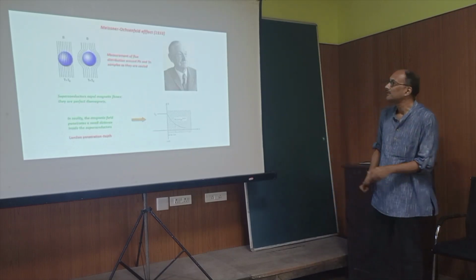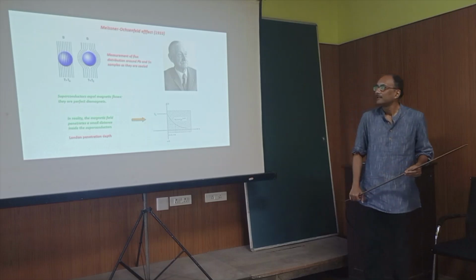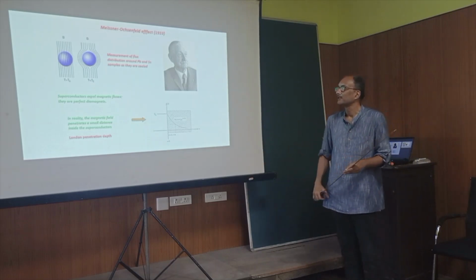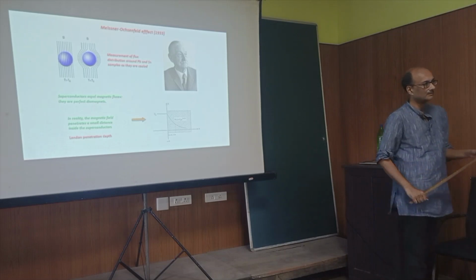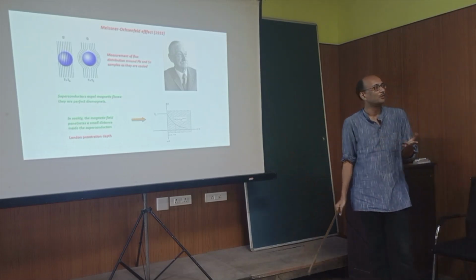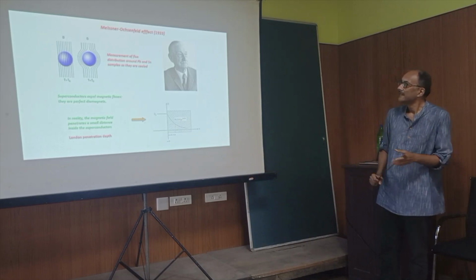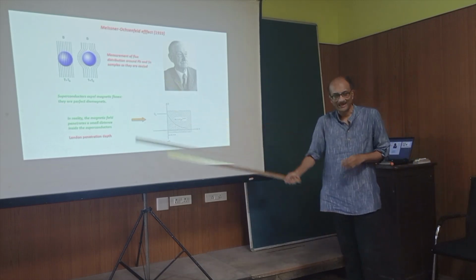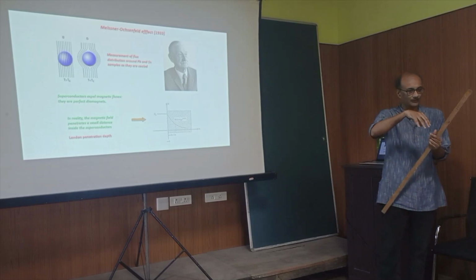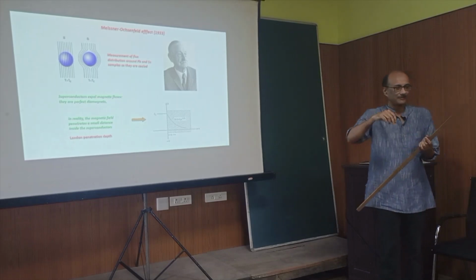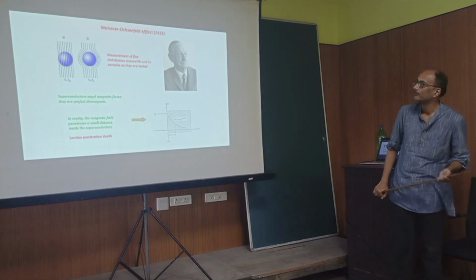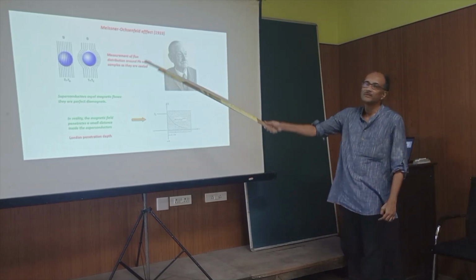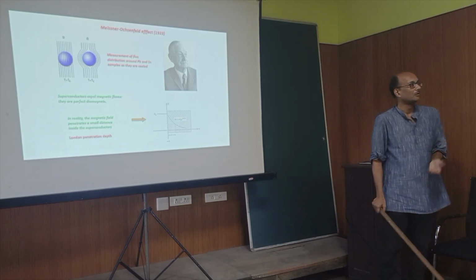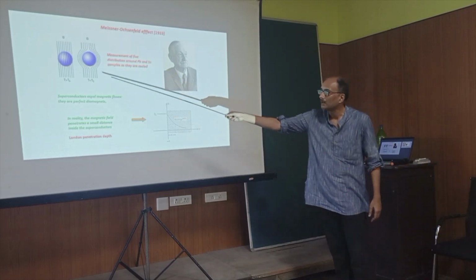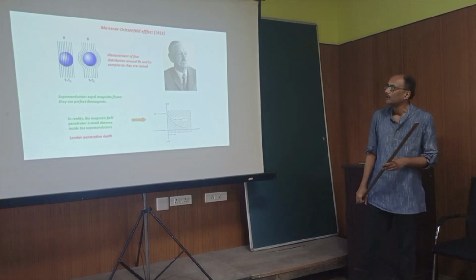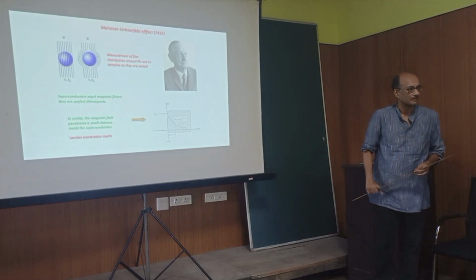when this gentleman, Meissner, and his student Ostenfeld essentially found out something really interesting. So this was about 21 years from 1912. Okay? So what they found is that they were looking into these magnetic field lines. You know, this experiment that all of you do at some point. You put a magnetic material and try to map out field lines around that material. So he was doing the same thing but at a very low temperature, where he could essentially lower the temperature of the sample so that it goes into a superconducting state.